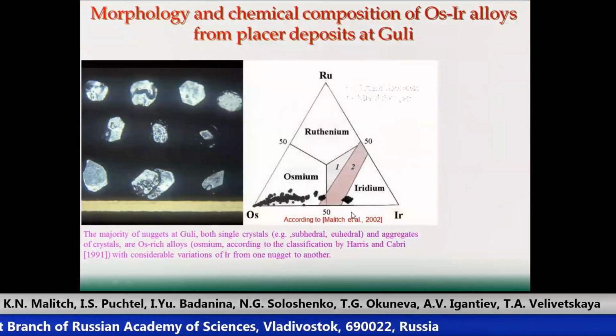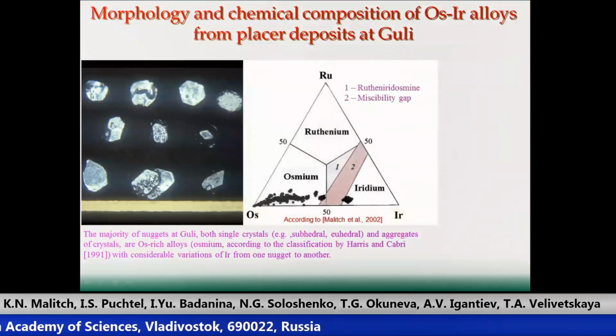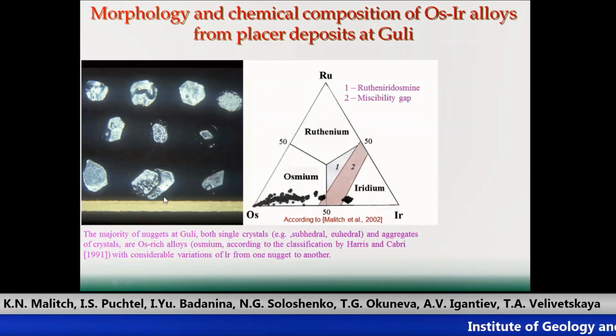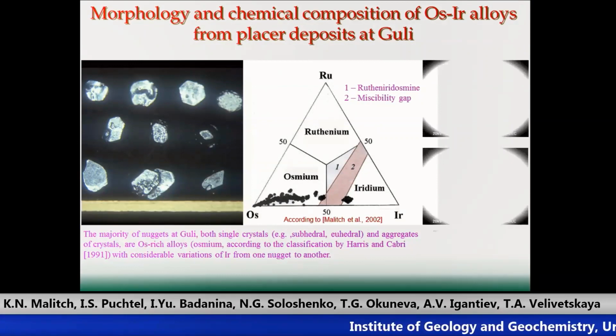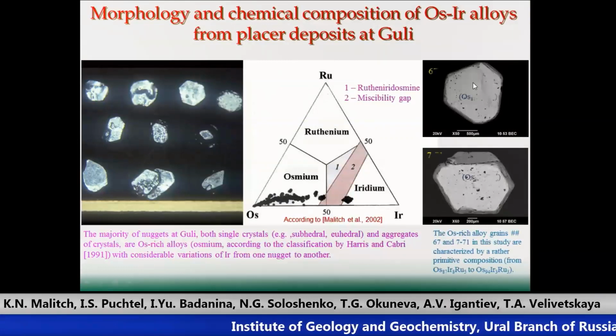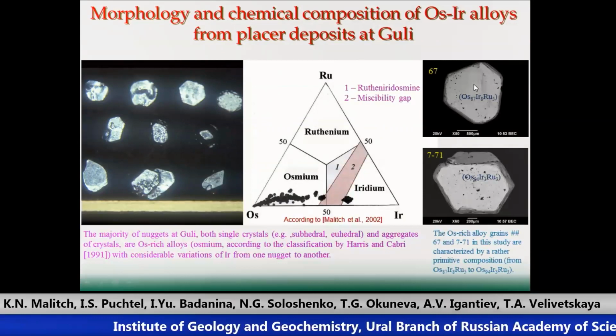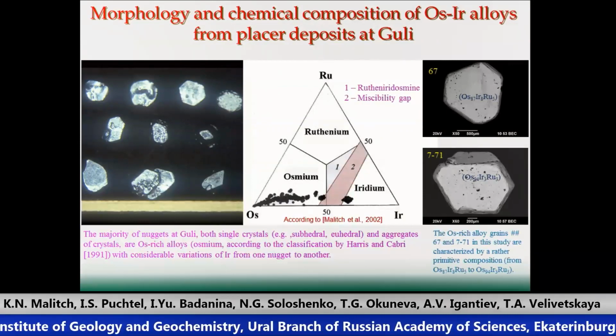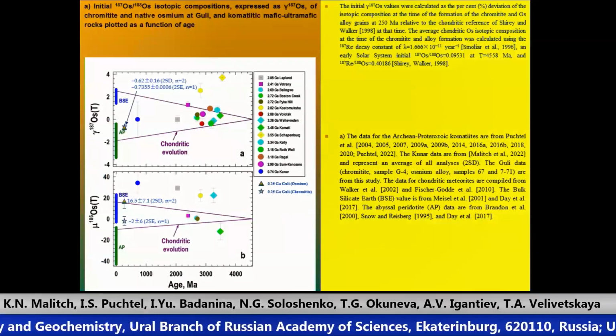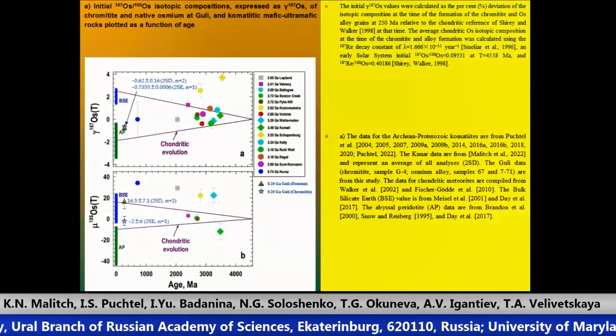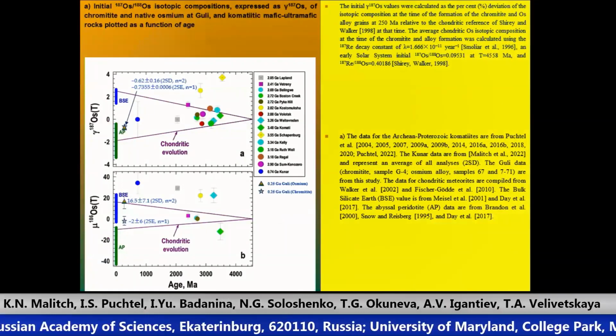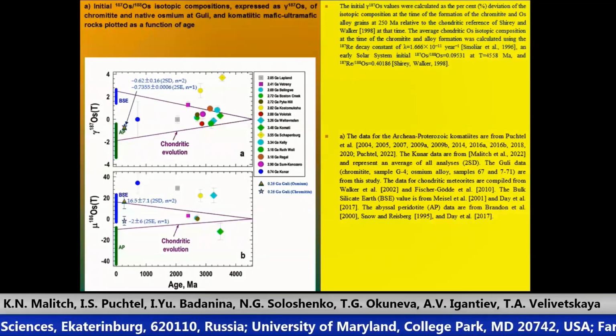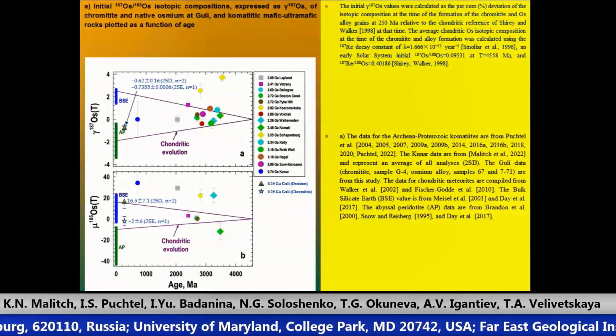The majority of nuggets at Guli, both single crystals and polyphase aggregates, are osmium-rich alloys, osmium according to the classification of Harris and Cabri, with considerable variation of iridium from one nugget to another. The osmium-rich alloys in this study are characterized by rather primitive composition. We adopt in this study the formation age of 250 million years for the chromitite and associated PGM.